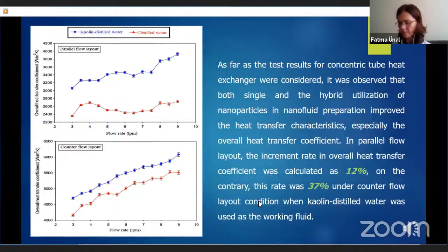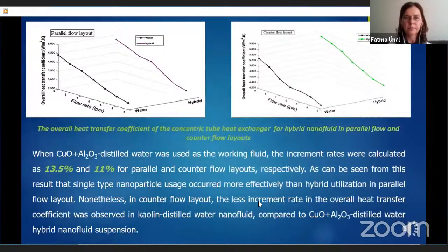In parallel flow layout, the increment rate in overall heat transfer coefficient was calculated as 12%. On the contrary, this rate was 37% under counterflow layout condition, when kaolin distilled water was used as the working fluid in heat exchangers. The overall heat transfer coefficients of the concentric tube heat exchanger for hybrid nanofluids in parallel flow and counterflow layouts can be seen in this figure. When copper oxide alumina distilled water was used as a working fluid, the increment rates were calculated as 13.5% and 11% for parallel and counterflow layouts respectively.